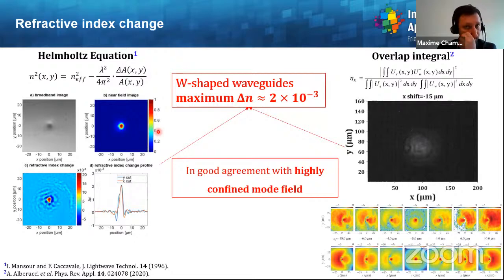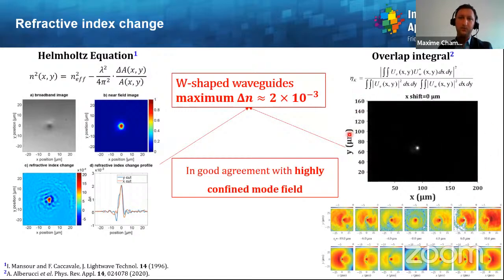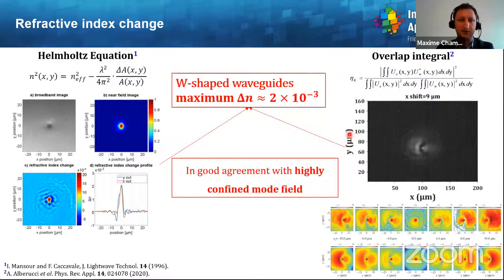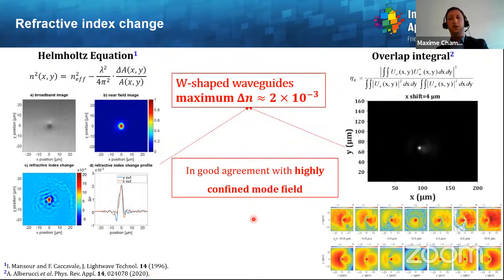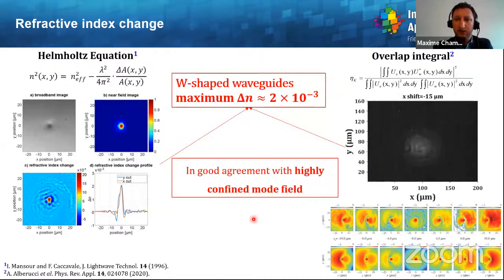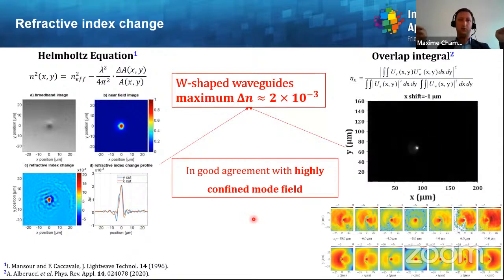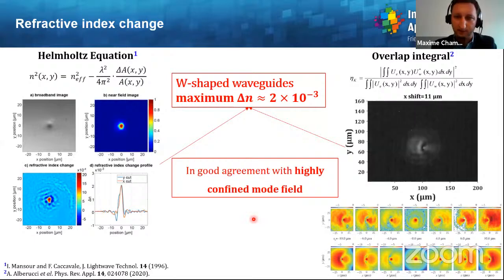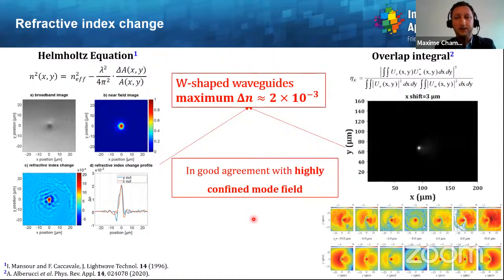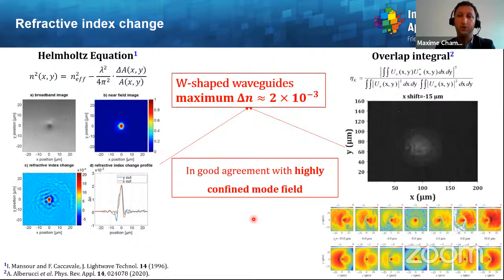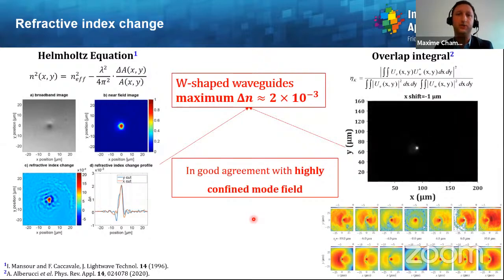Concerning the refractive index change, we have estimated it by coupling theory with Helmholtz equation and overlap integral, and also, as you can see here on this video, some shift measurements that are detailed in a recent paper from our group. So the reference 2 here on these slides, which allow us to conclude that the waveguides are W-shaped, meaning that you start with a negative refractive index, then a peak of positive refractive index. And the maximum refractive index in this case is around 2 times 10 to the minus 3. And this is in good agreement with highly confined modes. So in the end, we have a single mode waveguide with low losses.